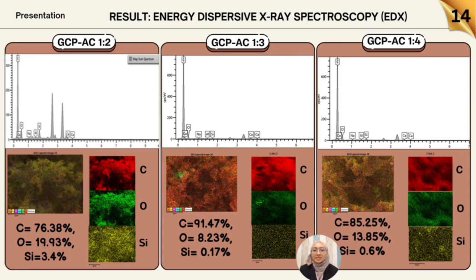Results for energy dispersive X-ray spectroscopy, which is EDX. EDX analysis confirmed that the 1 to 3 sample had the highest carbon content at 91.47% with minimal impurities. This carbon purity is crucial for maintaining high conductivity in battery applications. The other samples had lower carbon content and higher oxygen levels, which may hinder conductivity and reduce performance.